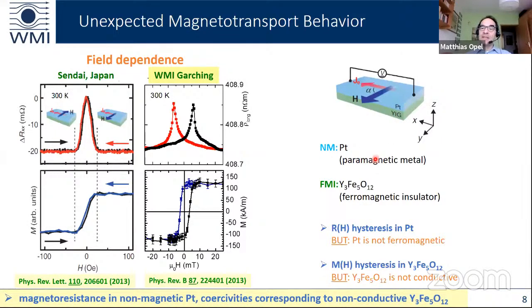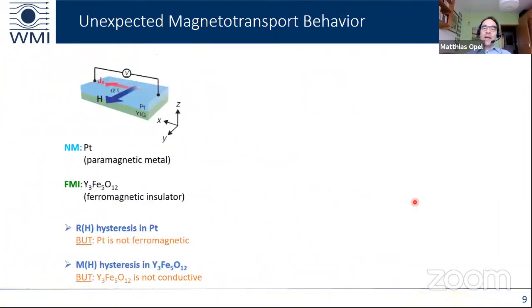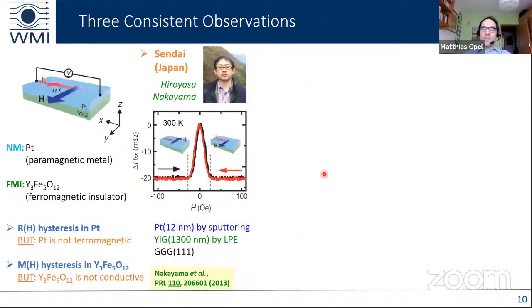Platinum is a paramagnetic metal responsible for the resistivity. YIG is a ferromagnetic insulator responsible for the ferromagnetic hysteresis. But we also see a hysteresis in the resistivity in platinum, although platinum is not ferromagnetic. And we see this magnetic hysteresis in YIG, although YIG is not conductive. So as I told you, the very same